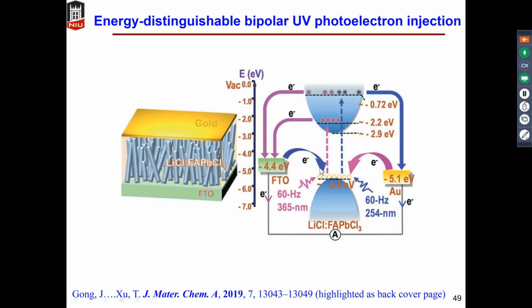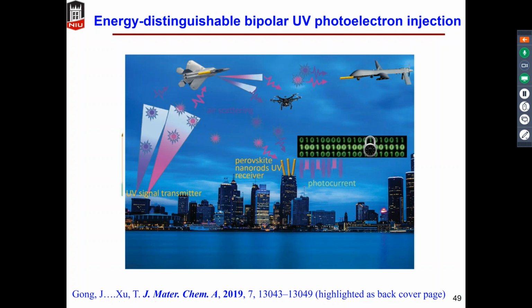So we think that because the FAPbCl3-based perovskite has very good absorption in the deep UV region, when you have long wavelength UV, the electrons only go to the conduction band, the hot state here, and then they are injected into the FTO side. But when you have high energy UV photons, they excite the photoelectrons to a very high level of hot states in the perovskite material. And in this state, the electrons can go either way. So that causes the cancellation of the currents and causes the current to go below the baseline. This work was highlighted as the back cover page by JMCA.